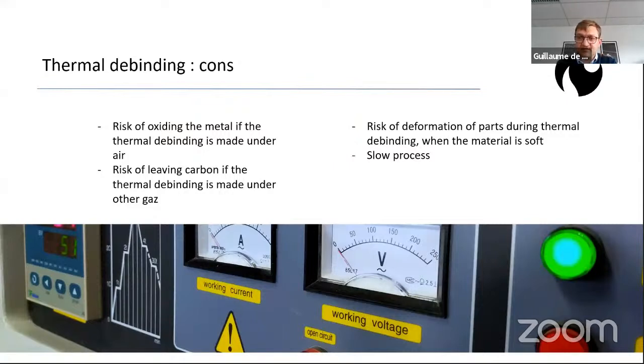The rest is also about the chemistry of the material. You will have to choose between debinding under air or under neutral gas, and both of them have some problematics. If you do it under air, you risk oxidizing the material during this thermal process, and if you do it under neutral gas, you have the risk of leaving some carbon in the material, which would not be good for the final material. So that's really a very fine compromise you need to find.